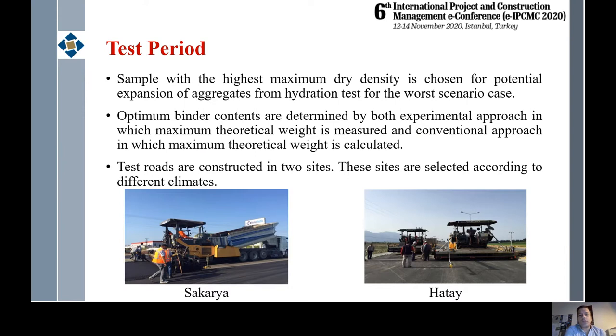The sample with the highest maximum dry density is chosen for the potential expansion of aggregates from hydration tests for the worst case scenario. Optimum binder contents are determined by both an experimental approach, in which maximum theoretical weight is measured, and a conventional approach, in which maximum theoretical weight is calculated.